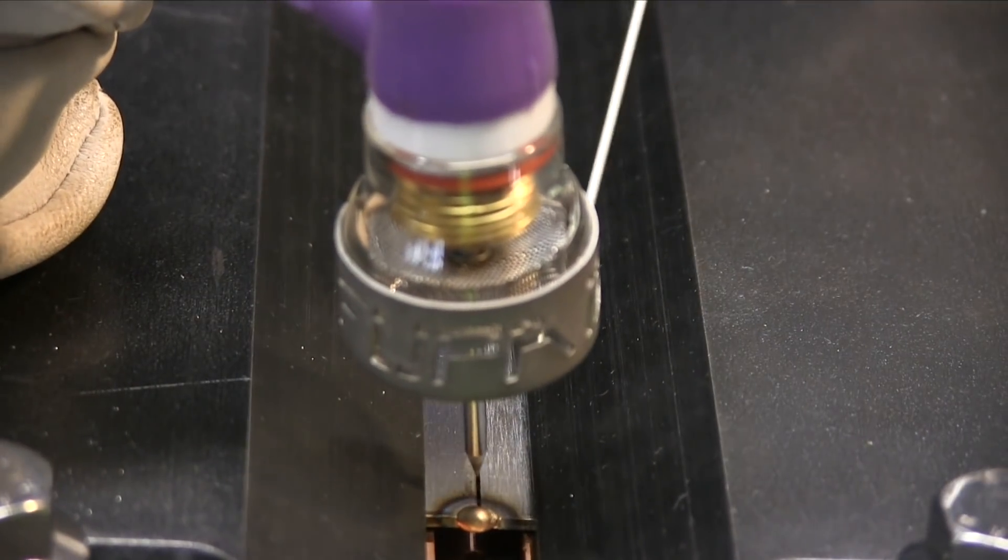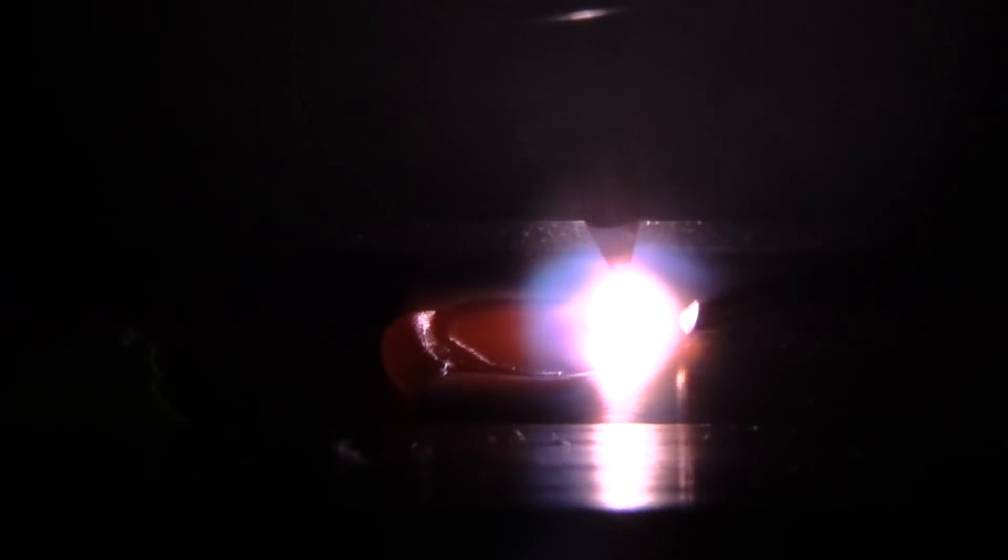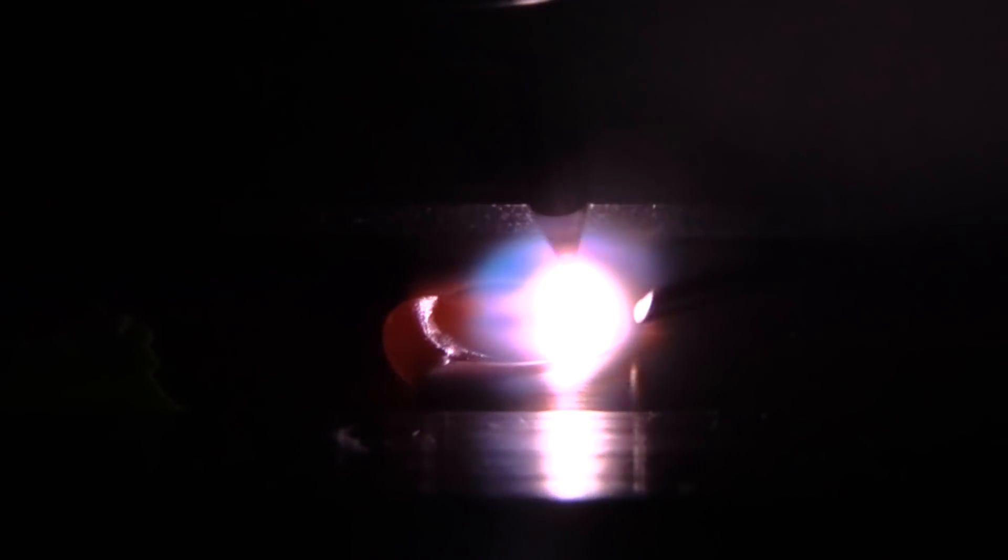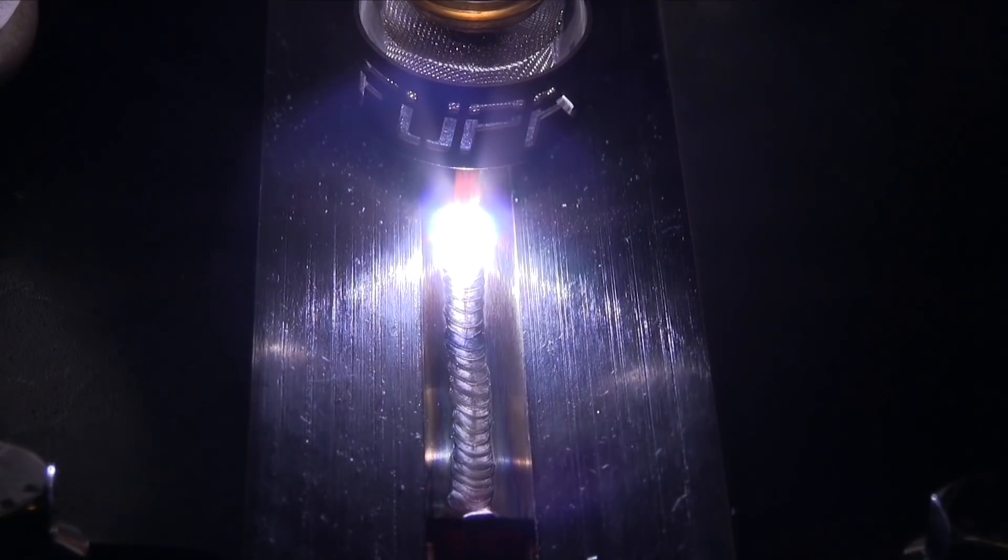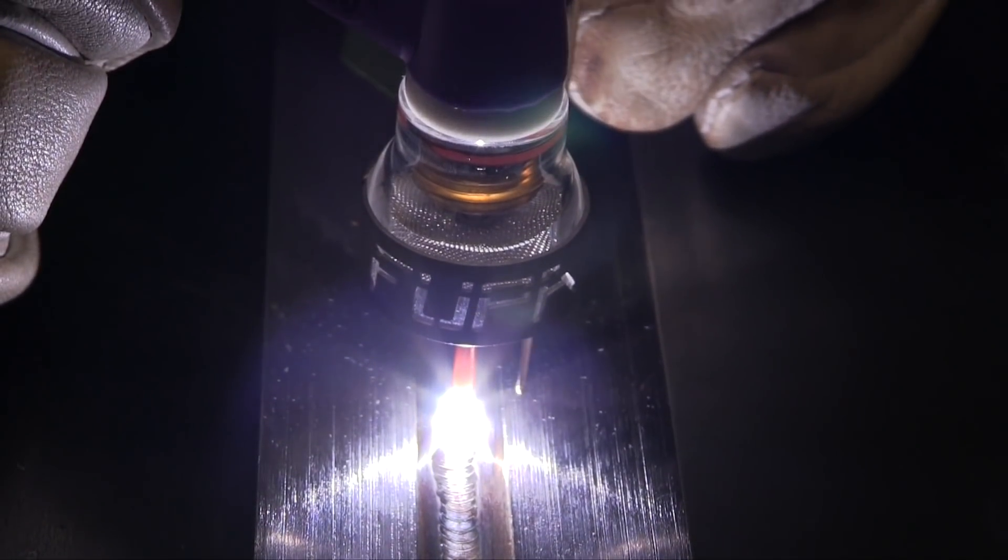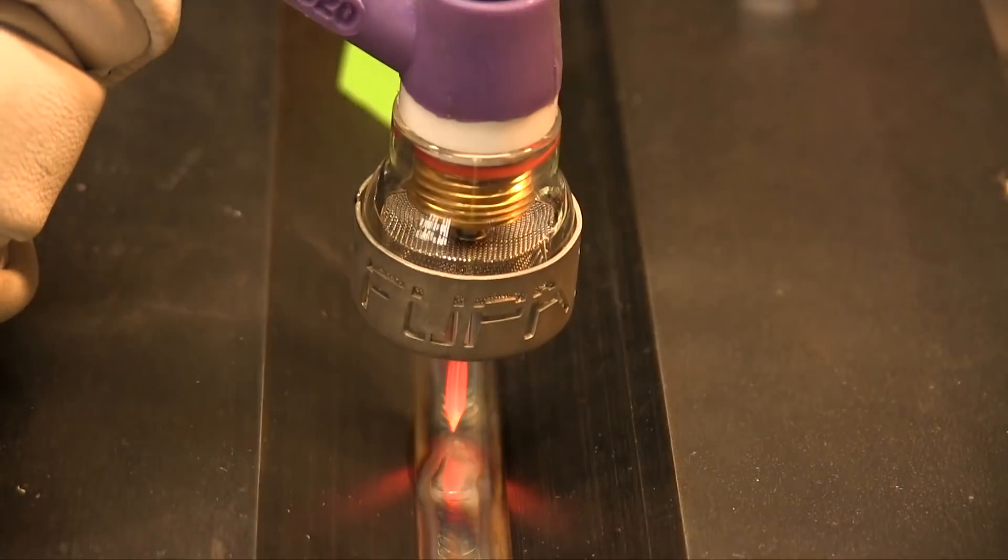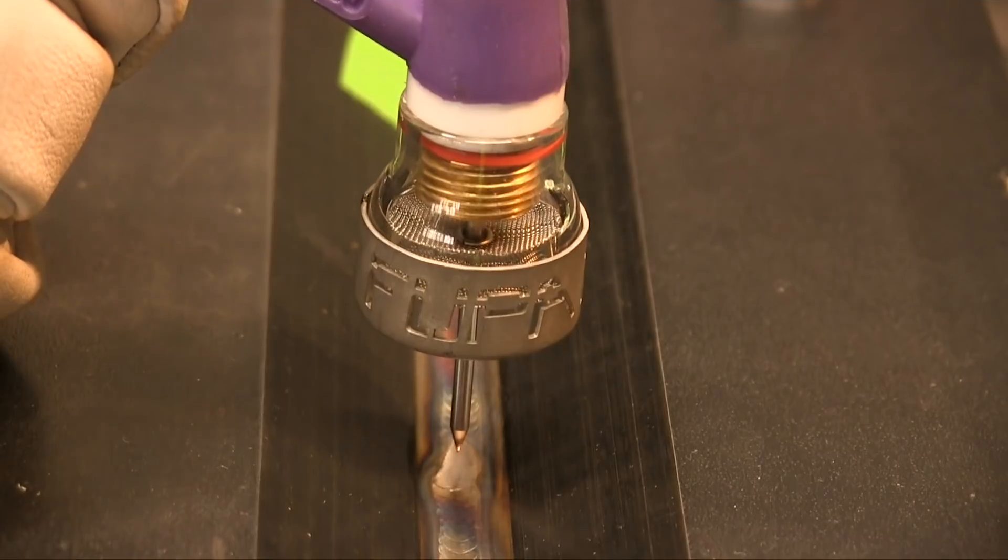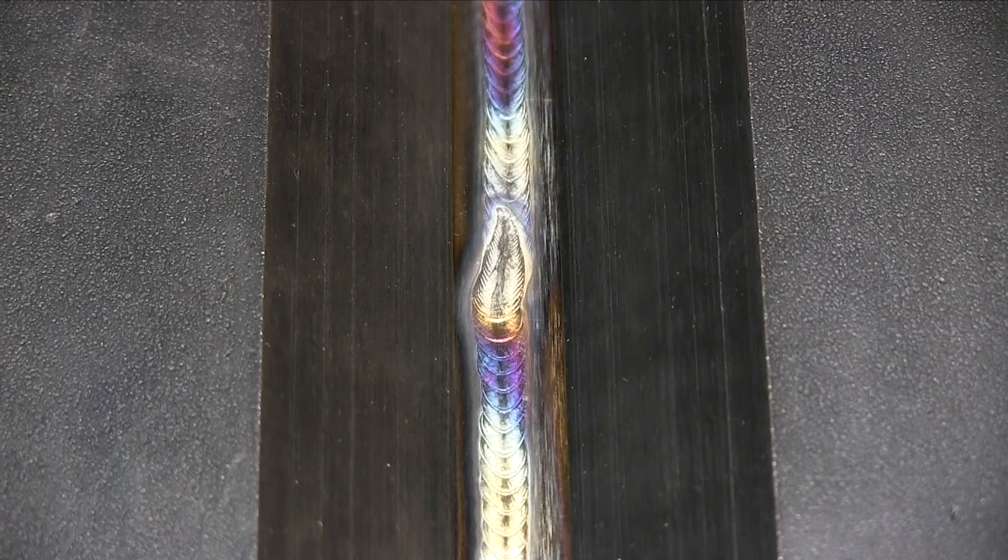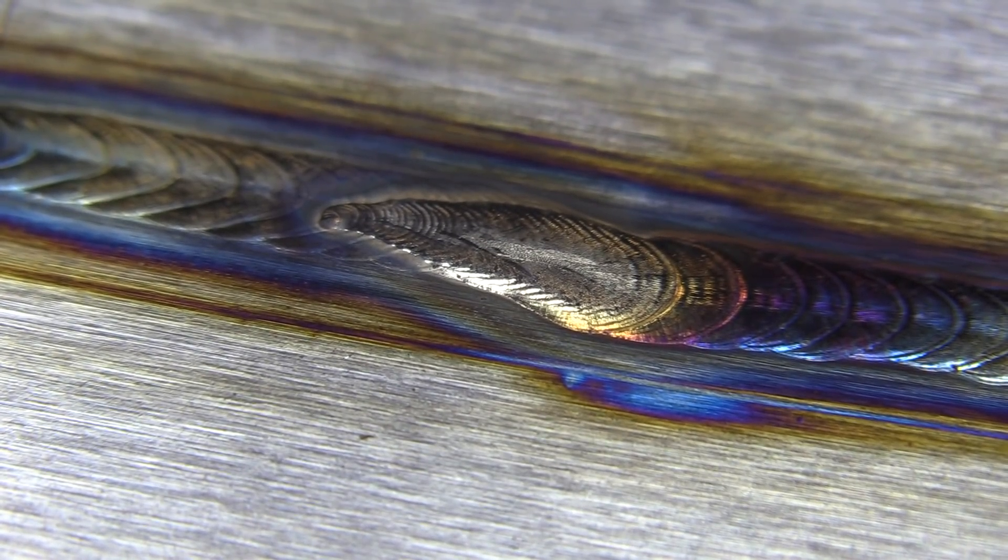Now, something I didn't mention. There's a reason why I'm welding this in halves. And it's called back step welding when I weld to a previous weld. And that basically is because this is what I required when I had to administer these tests. I thought it was a pretty bad idea not to have any stops and starts. So this at least demonstrates the ability to taper off and not leave a crater crack or crater eye on some of these crack sensitive alloys. So you can see there in slow motion, it works just as well coming from a tack as it does tying into a tack. And then when I tie into the previous weld here, I just keep the torch moving, add less and less filler and kind of comet trail on out. And that wound up being about the best technique I could find for crack sensitive alloys like Inconel 718, 4130 chromoly or 15-7 pH stainless.